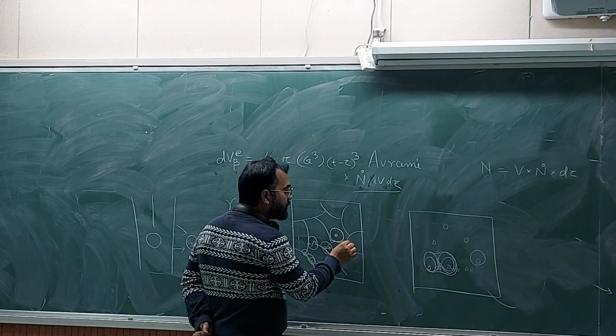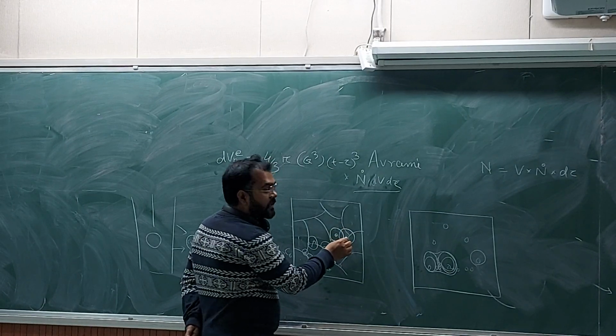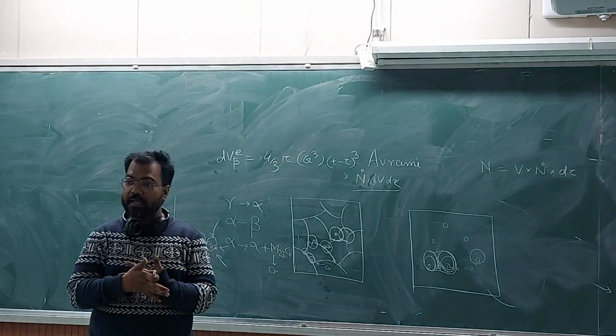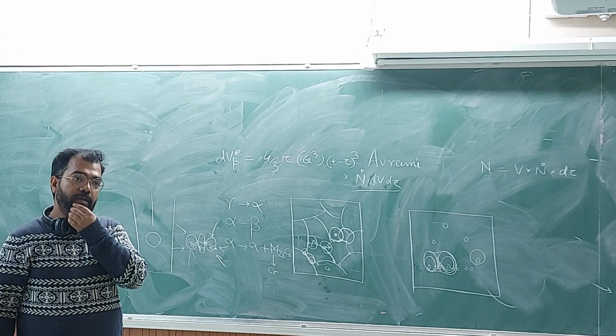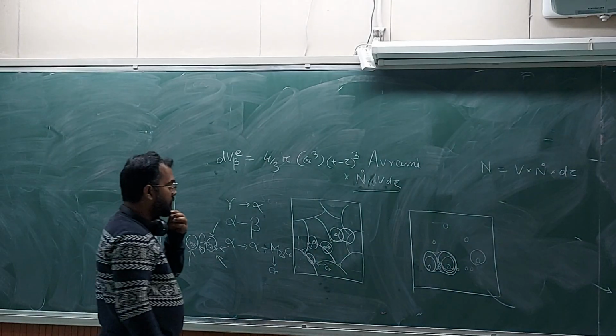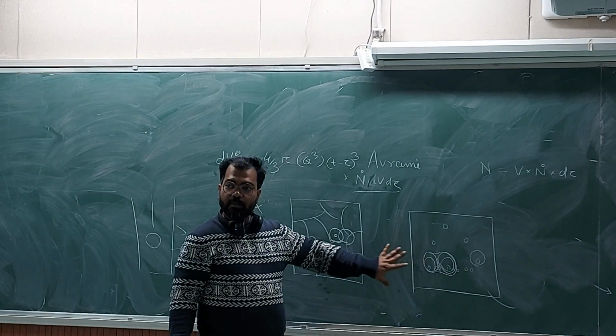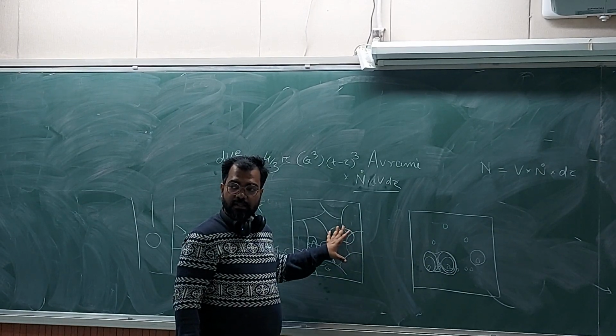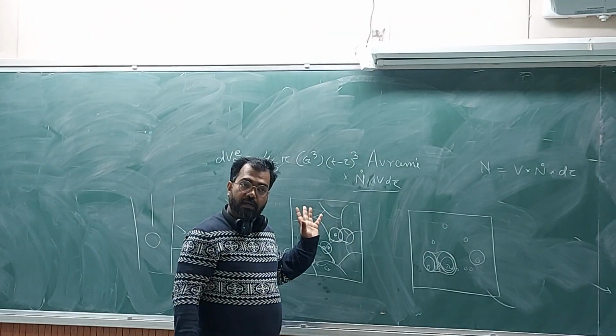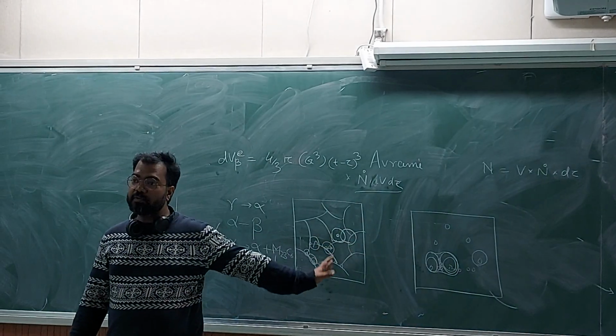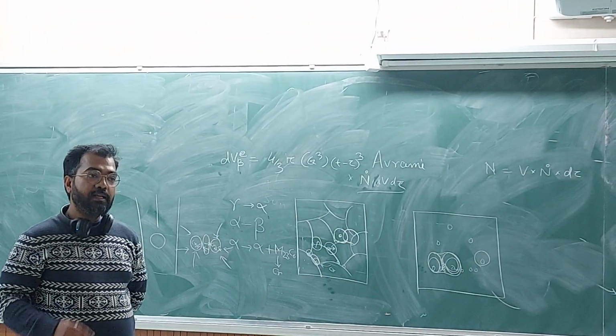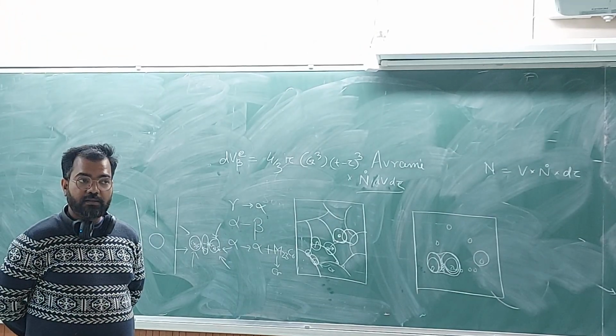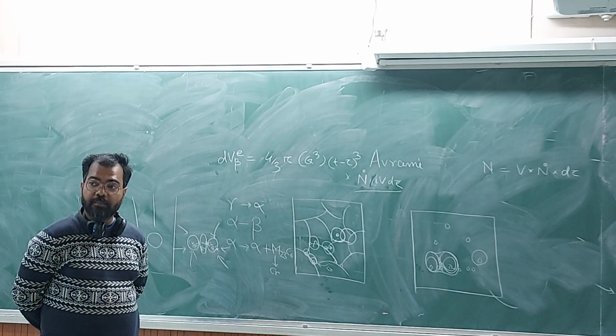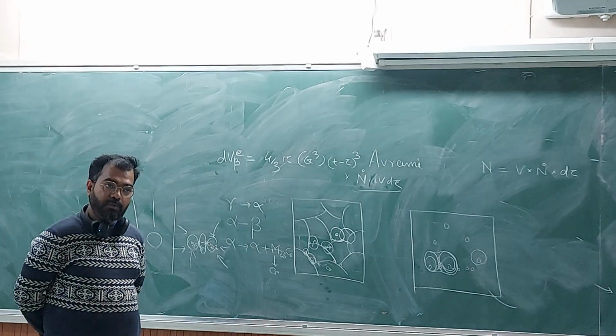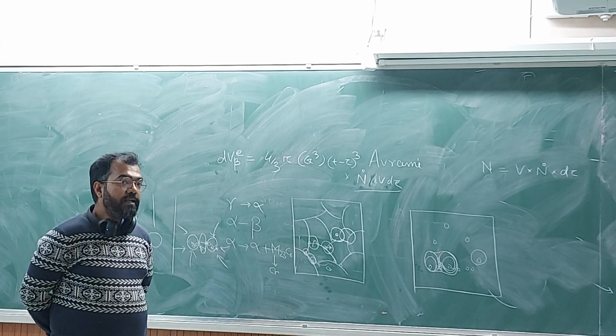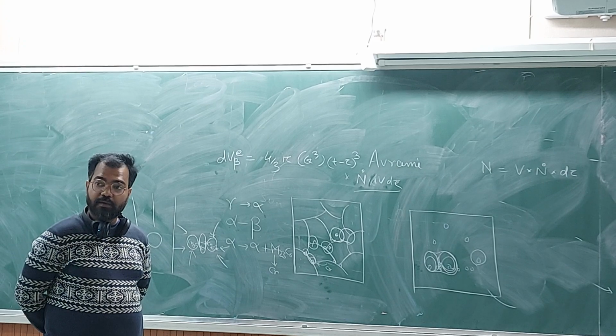And secondly, we are not stopping the growth of two transformed regions into each other. That is also not taken care of in the equation. Okay. So the phenomena is, until growth of voids, the phenomena of solid to solid transformation or precipitation. Actually, precipitation is closer to the phenomena of ductile damage until you have growth of voids happening. So as long as that is happening, that is exactly the same. The mathematics, the kinetics is exactly the same in both cases. It starts differing when you have coalescence happening in voids.